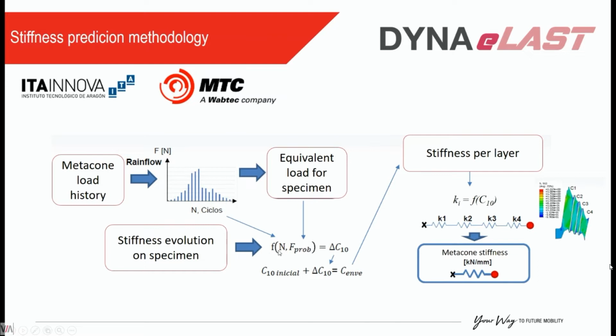For the evolution, we use the C10 of a neo-Hookean hyperelastic material, and we track its evolution. If we are able to predict how C10 is going to evolve for a given cyclic loading, we can determine the stiffness per layer of rubber in between metal sheets. With that, we can calculate the stiffness, and then it's a series association to get the global stiffness.